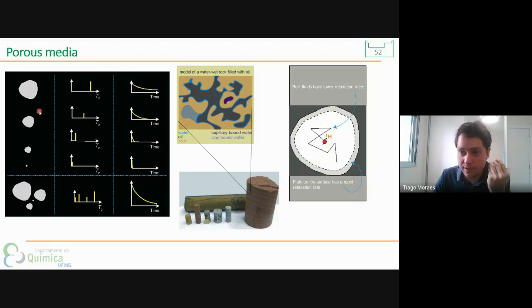So, for example, for small pores, you have very short relaxation times for water. If you have a bigger pore, you have a longer relaxation time, and for a bigger one, longer, almost until free water, right? So when you acquire a signal from a rock that is saturated with water, or even water and oil and gas, you will obtain a total signal that comes from all the signals that your coil, the sensor, detects, right? So the total signal that you detect has all this information, from the small pores to the big ones, from oil, from gas, from water.